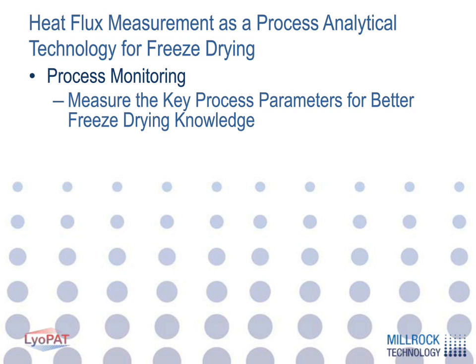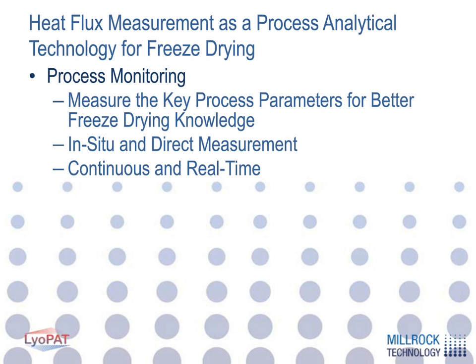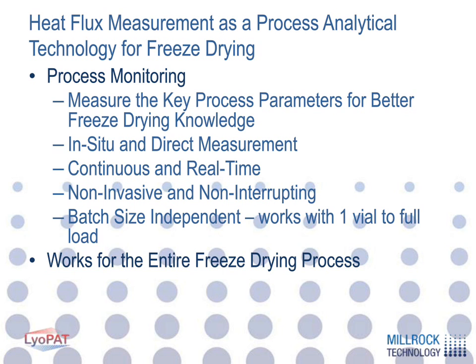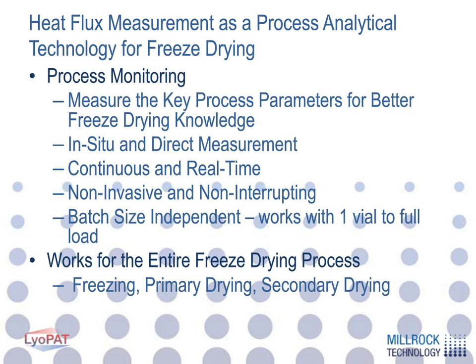Heat flux measurement as a process analytical technology can be used to measure all sorts of neat things during the process. And one of the nice things about it is it's in situ during the entire process. It's continuous, real time, non-invasive, non-interrupting, and batch size independent. You could use it for single vials if you wanted to. Works a little bit better with more than a single vial, but certainly can give you some neat information. But one of the key things is that it works for the entire freeze-drying process. That includes the freezing process, the primary drying process, and the secondary drying process. In addition, it's freeze-dryer independent, so it doesn't necessarily have to be on any specific type of freeze-dryer.